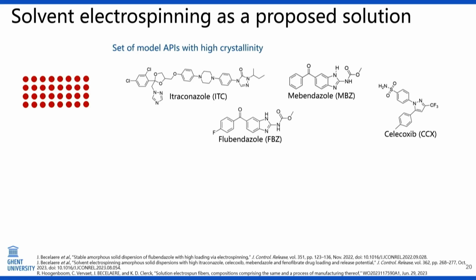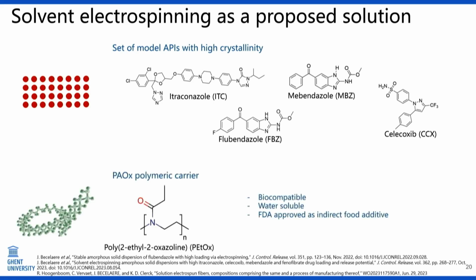We did this for a range of model APIs which have all proven pharmaceutical efficiency, but suffer from a very low solubility. And as a polymer carrier, we used our polyoxazoline, PEtOx, because of its very high water solubility, also biocompatibility, and FDA approved as a food additive. In addition, it's important that the polymer carrier shows interactions with the drugs to stabilize the dispersion.